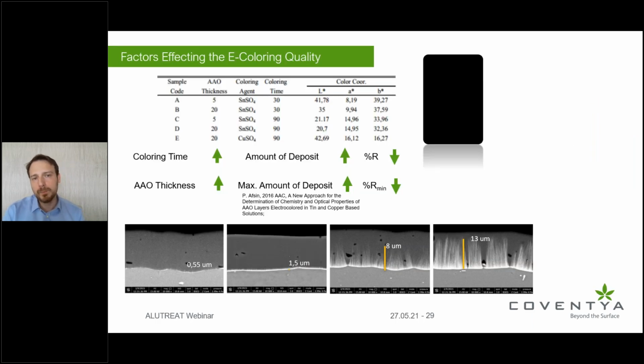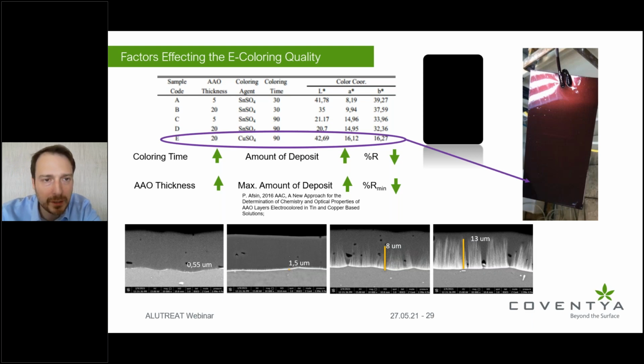Well, I know that this is another question: how can we change the A and B color values? So how can we shift the color a little bit? Quite frankly, the color or shade, the A and B values, are more affected by what you're precipitating. As we can see here, this is copper sulfate-based chemistry, which has a reddish color, rather than being affected by the coloring parameters themselves. They do change the shade or hue, and sometimes can create huge problems. But to make a drastic change from a reddish hue to a bluish hue, you need to use a different chemistry.